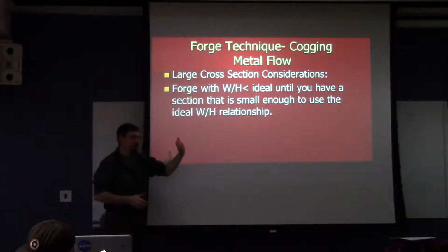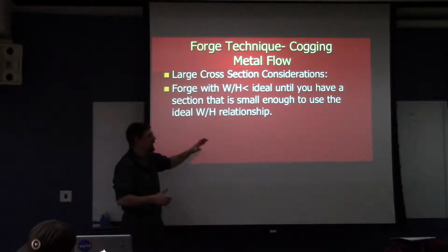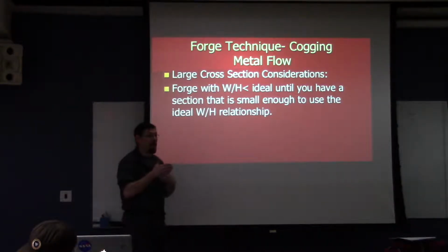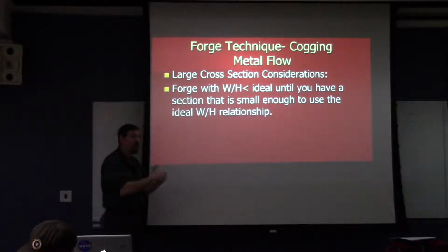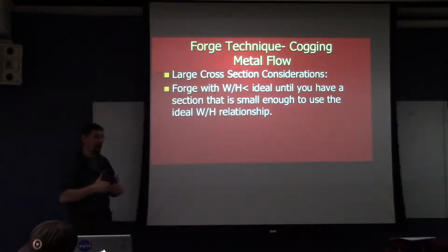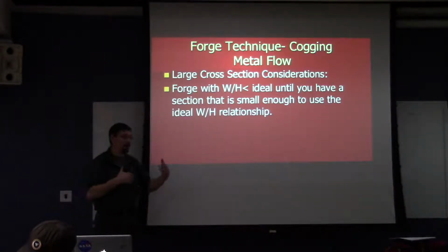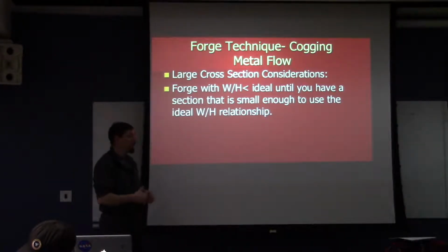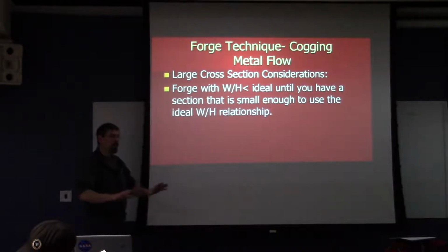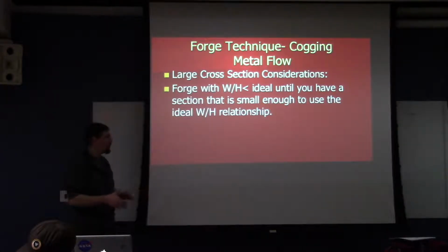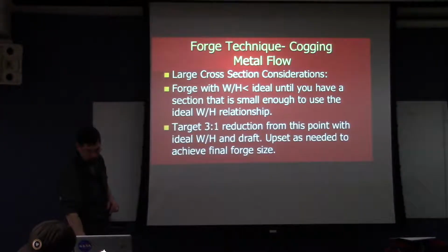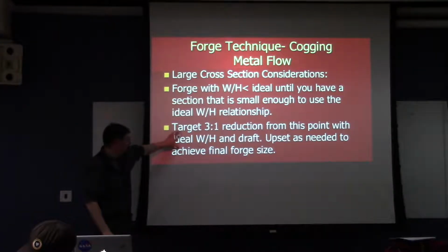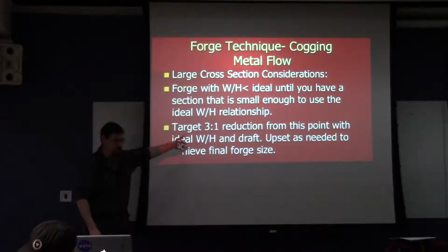And the part might be hot enough they could continue deforming it with this kind of a practice, but they're going to stop at a bigger size, put it back in the furnace to make sure that when they come back out, they can get that 3-to-1 effective reduction. And as long as they do that, it's perfectly fine, and we can still make very high quality parts that achieve all the goals we've set for ourselves. And that's this 3-to-1, this is my longhand way of saying effective reduction.